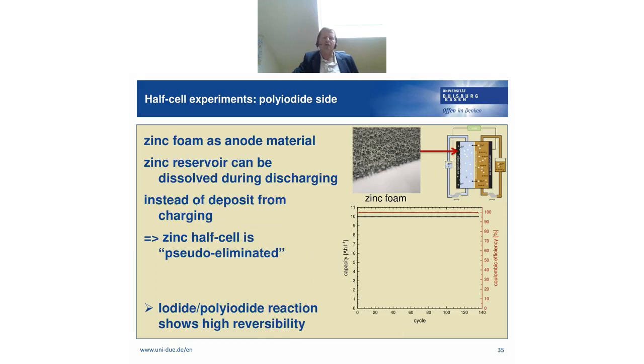So the question for us is which side, the anode or the cathode side, is really limiting the performance at the moment. So we devised some half-cell experiments. I will show you here one experiment for the polyiodide side. We use a zinc foam as anode material, and this acts as a zinc reservoir that can be dissolved during discharging instead of the zinc deposit from the charging. Like this, we can eliminate the zinc half cell, so to say, and only concentrate on the polyiodide side.